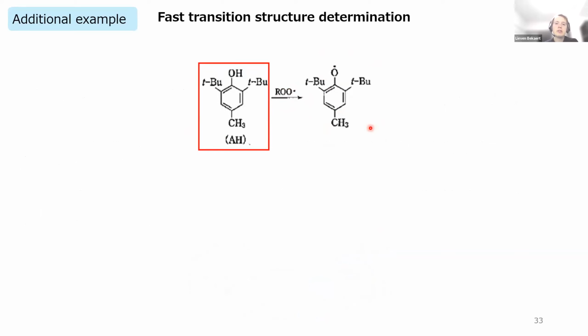Now, if you look at this reaction, it might seem very simple, it's not too large, but if you perform it with density functional theory, if you want to look at the activation energy, even with 64 cores, it takes more than a day. And in reality, it took more than a week or up to a month, because you have to find the right transition state structure, and only then can you have the right energy.